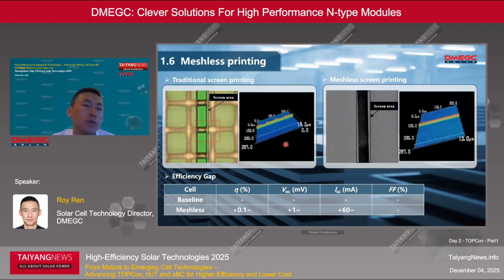This is meshless printing. It is a new type of screen printing technology. We can see that there are no steel wires in the printing area, which will greatly reduce the printing difficulty, reduce line width, and improve the transmission of current. So we can achieve an efficiency improvement of over 0.1%, mainly in VOC and ISC.